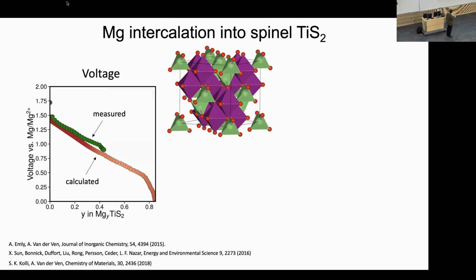And then a year later, Linda Nazar's group was successful in experimentally realizing this. They made a cell and used this as the cathode, and they inserted magnesium, and they got this green curve over here. So this was a prediction before the experiments were done. And you can see very good qualitative agreement and also very good quantitative agreement. Now, the quantitative agreement is because density functional theory, which is the starting point, is very accurate for sulfides. But note, we've only considered magnesium vacancy disorder. We're not considering vibrations. We're not considering other excitations. And just by considering the entropy of magnesium vacancy disorder, that's sufficient to capture all the qualitative trends in this voltage curve as a function of the magnesium content.